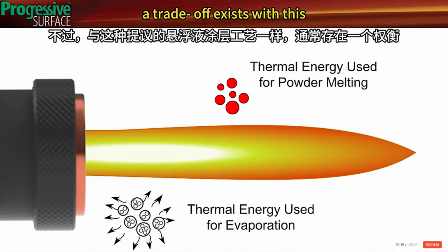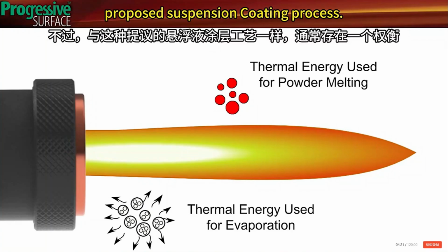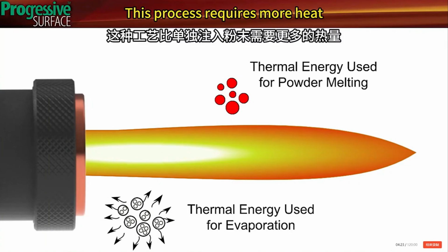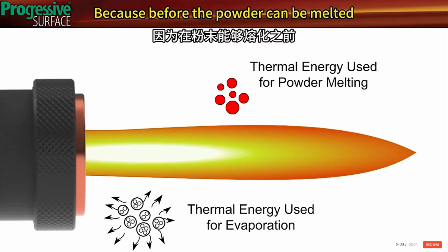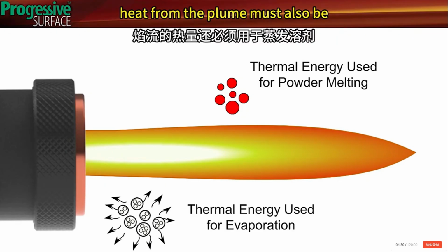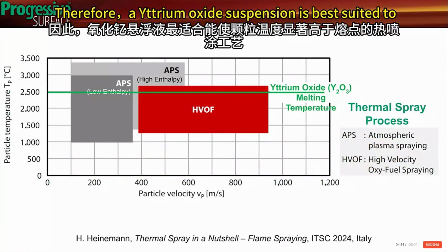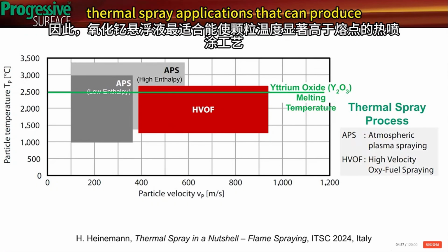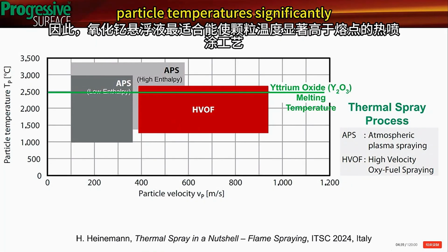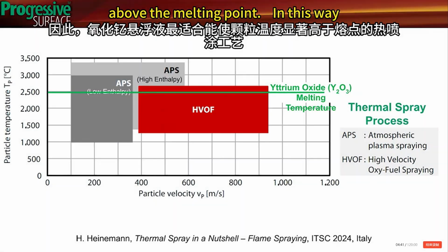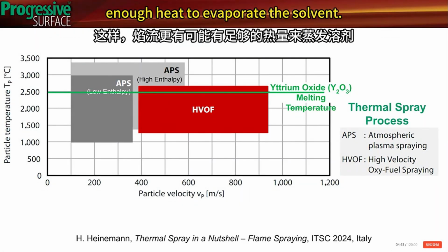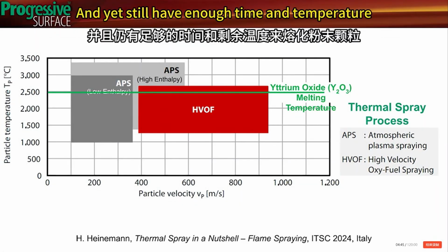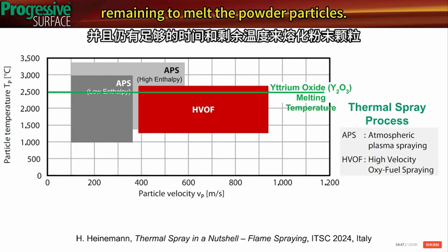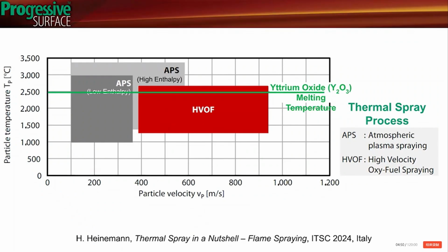As is typical though, a trade-off exists with this proposed suspension coating process. This process requires more heat than injecting the powder alone, because before the powder can be melted, heat from the plume must also be used to evaporate the solvent. Therefore, a yttrium oxide suspension is best suited to thermal spray applications that can produce particle temperatures significantly above the melting point. In this way, the plume is more likely to have enough heat to evaporate the solvent and yet still have enough time and temperature remaining to melt the powder particles.